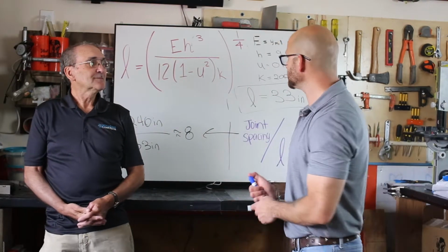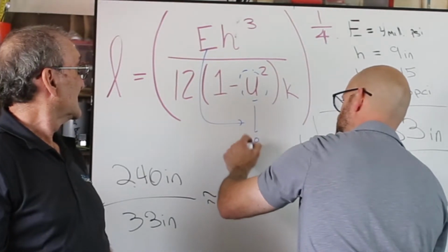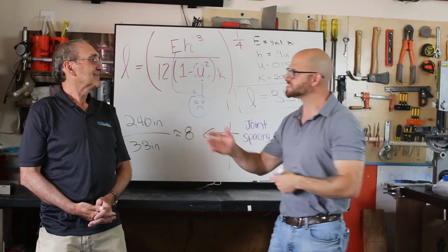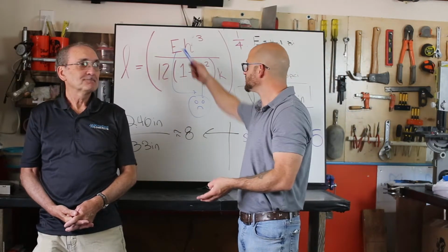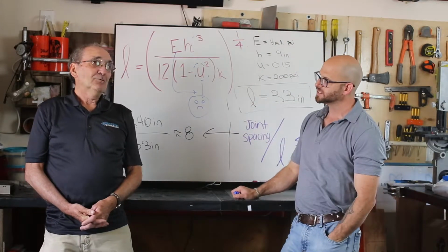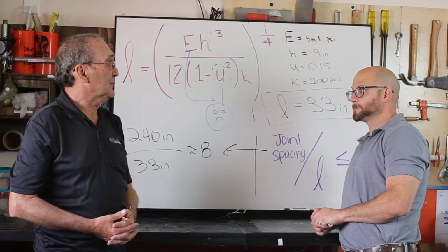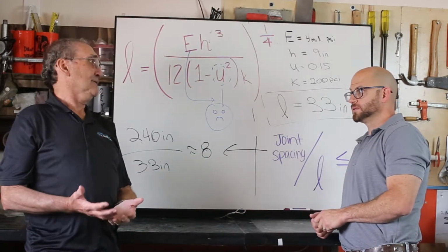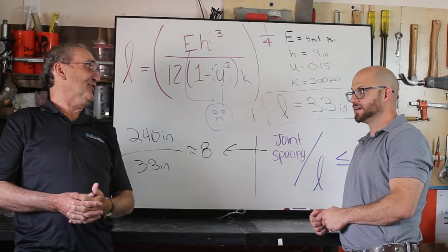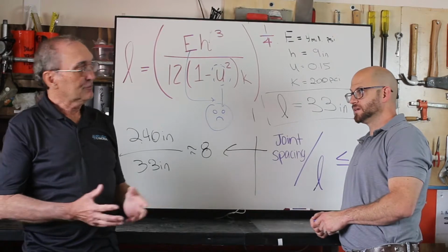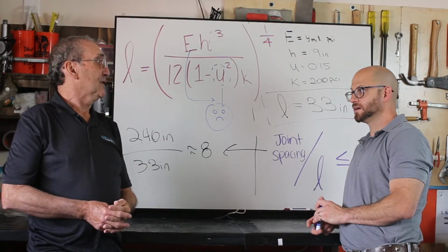One of the things that bothers me about this, David, is these two values. I don't like those values because it is forcing us to assume that they're never going to change. There are even values in the FAA guidance that tell you this is 4 million, this is 0.15. What's the problem with that, David? Well, not all concrete's the same. We looked at typical values that we suggested as an example, and we plugged those in. 4 million is a typical value, but it's not what all concrete is. That's why this is a variable. 0.15, I might call that 0.2 myself, from work we did at the Bureau Lab. So it's good that they're variables. We plugged in some typical values just to give you an idea, but if it was me, I'd use real values for real projects.